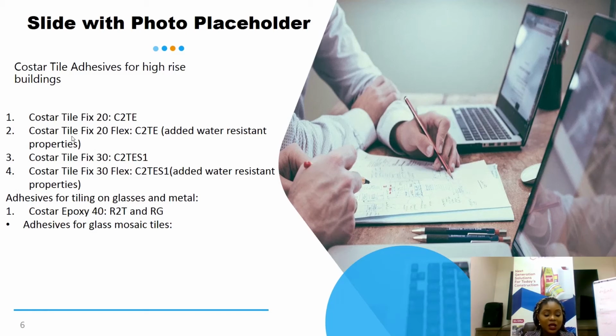So basically, it has waterproofing properties, so water can't flow through it. And the beautiful thing about Costar Tile Fix 20 Flex is that it has added water resistant properties and also meets this standard, which is a very good pick for tiling high-rise buildings. Then for Costar Tile Fix 30, we have the C2TE S1, and it's been improved actually to S2, not S1 anymore. And this is a very good pick for tiling for high rise.